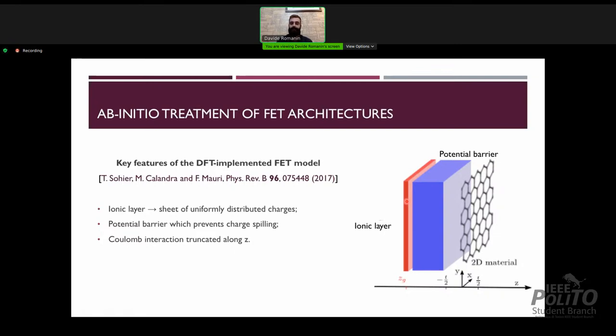And finally, if we work with a plane wave implementation of DFT, the system is periodically repeated in all the directions. So in order to simulate a surface, we need to insert vacuum between different repetitions of the system in order to break the periodicity along one direction, for example, the one perpendicular to the surface. Therefore, the Coulomb interaction is also truncated in order to avoid spurious interaction with periodically repeated images along the non-periodic direction.